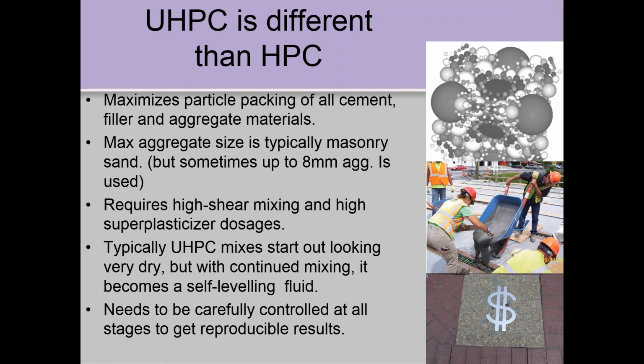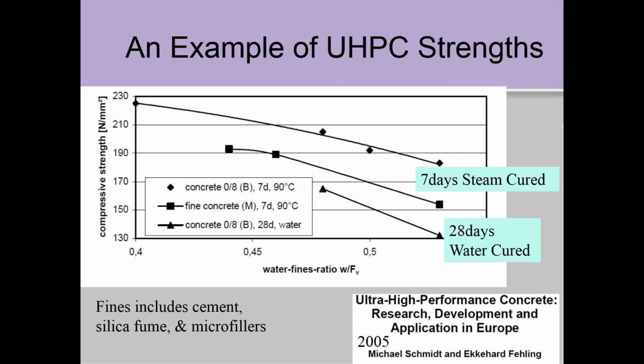But it shows them here using it for the joining panels for precast, some sort of precast deck unit there. Where they put in high-performance deck units, and then the rebars there, and they're putting in the filler strips, they're putting in the ultra-high performance material. And they consider all the fine materials in this, so not just cement and SCMs, but even things like ground powders of various sorts would be considered in this water fines ratio. And it shows the sort of strengths you can get at 7 days steam cured or 28 days water cured, the types of strengths we're talking about. This is an old paper, I just took it as an example of what you can get with these sorts of concretes. So it's a whole different animal.